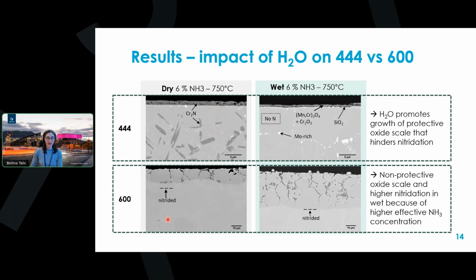For alloy 600, we see that the extent of nitridation is, as we saw from the mass gain, lower in dry conditions than in wet conditions. To understand this, we measured the degree of ammonia decomposition at the outlet of the test reactor using FTIR gas analysis. What we saw from this was that at 750 degrees and wet conditions, more of the ammonia was retained at the outlet compared to dry conditions. So to say it differently, we had more cracking of ammonia inside the reactor in dry conditions than in wet. So in practice, the alloys were exposed to a higher concentration of ammonia in wet conditions than in dry conditions. And this is why we probably see a higher degree of nitridation in wet.